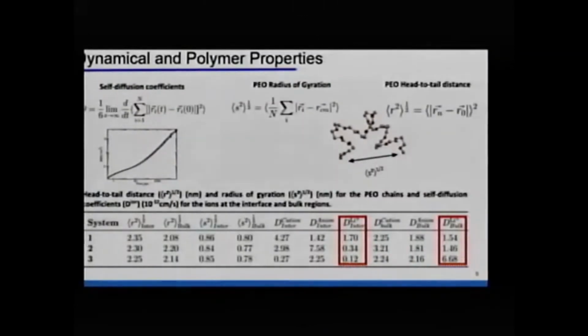I said in the beginning that the imidazolium cation is planar, so there is a ring, and because of this, the imidazolium cation can adopt a parallel stacking to the surface, and the same happens with the triazolide, because we have the triazole ring. So triazolide and imidazolium can adopt some kind of packing in the structure that creates some planes inside the interface, and this increases the lithium transport. This is a very well-known behavior in ionic liquids in the bulk phase. When we have planar ions in the system, the planes inside can decrease the energy barrier for the diffusivity of the